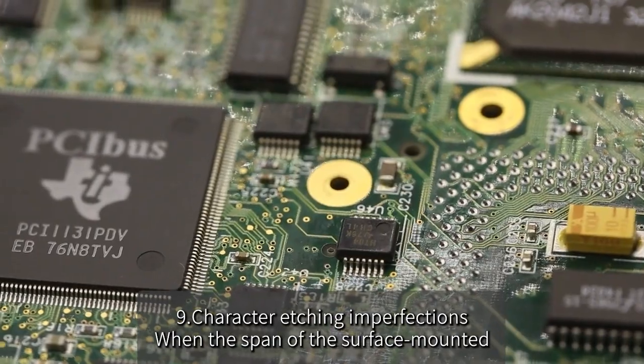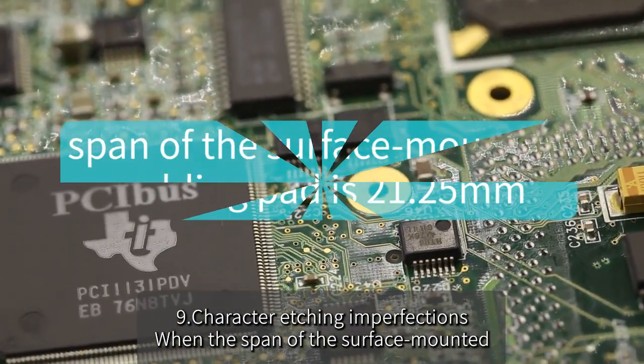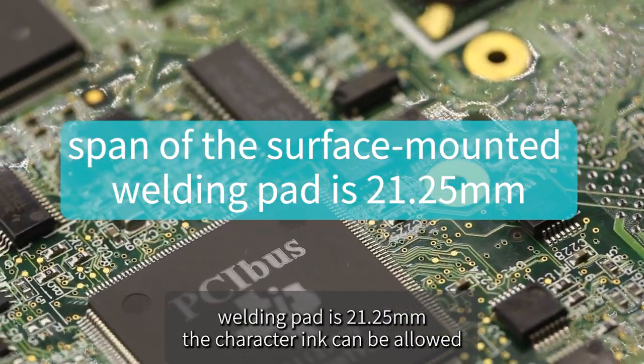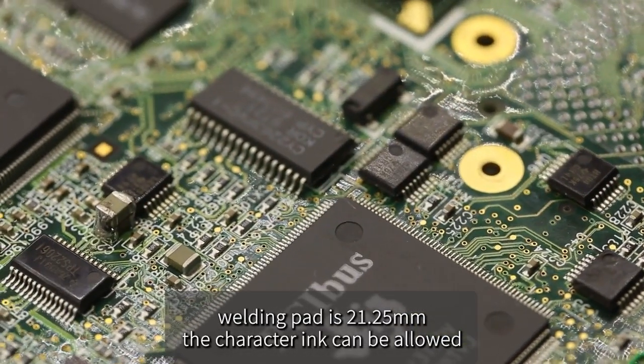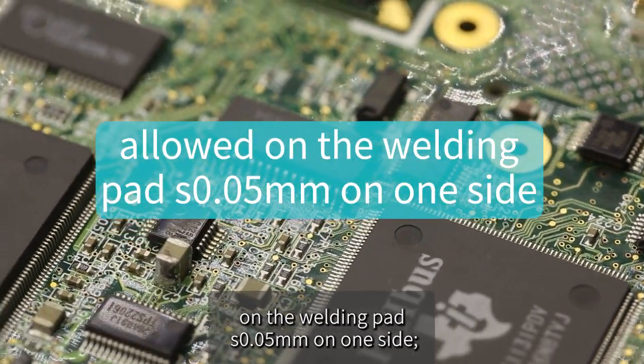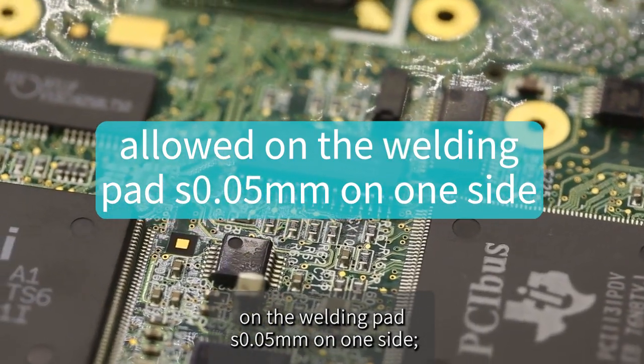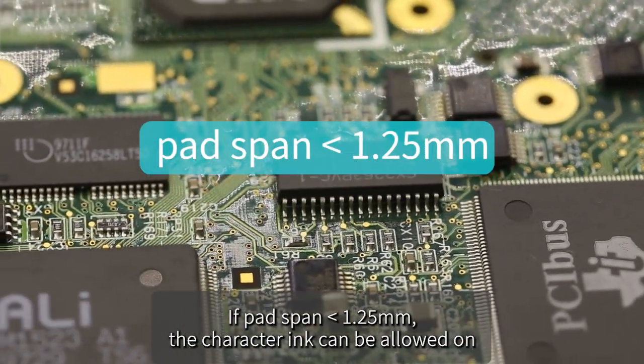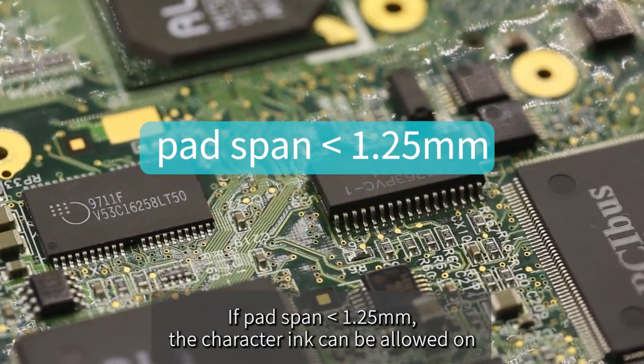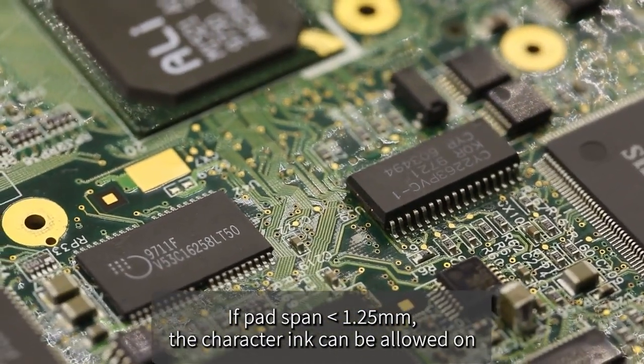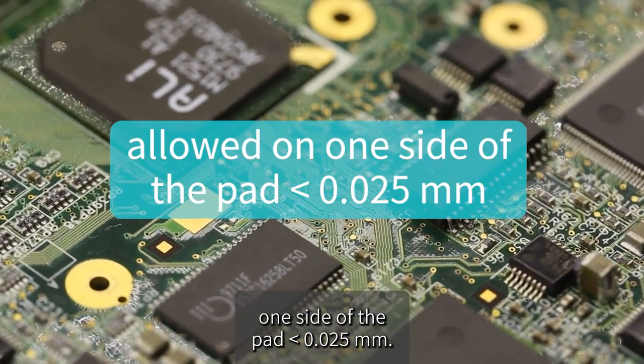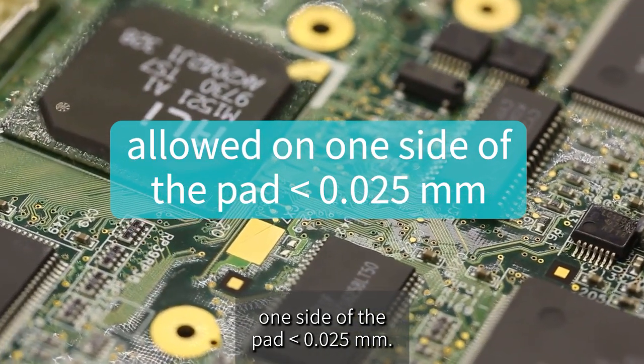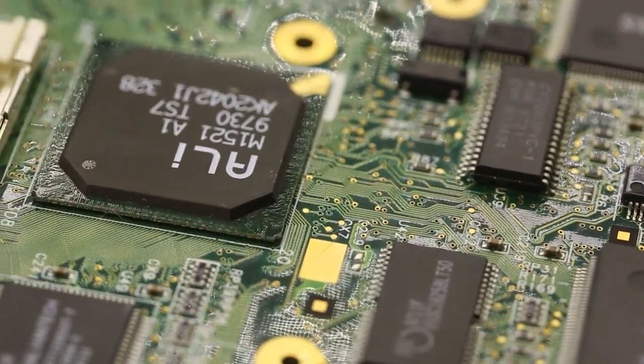9. Character etching imperfections. When the span of the surface-mounted welding pad is ≥1.25 mm, the character ink can be allowed on the welding pad ≤0.05 mm on one side. At pad span <1.25 mm, the character ink can be allowed on one side of the pad ≤0.025 mm.